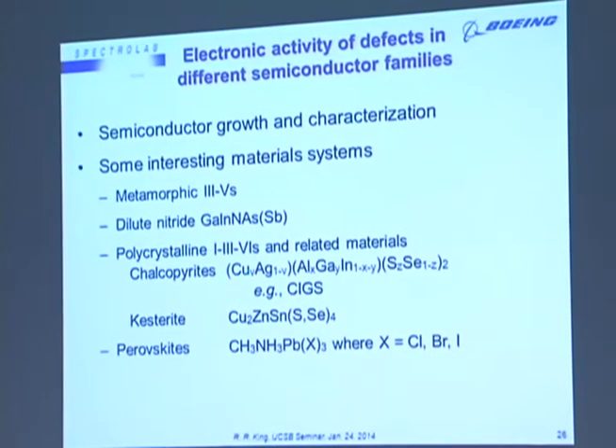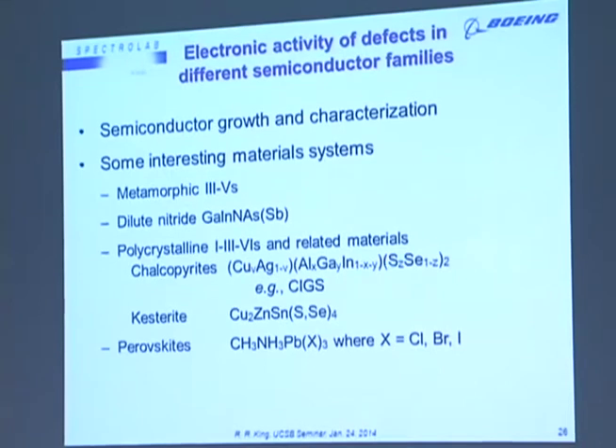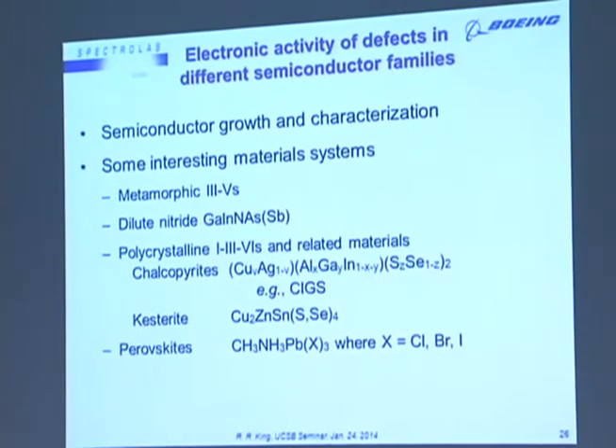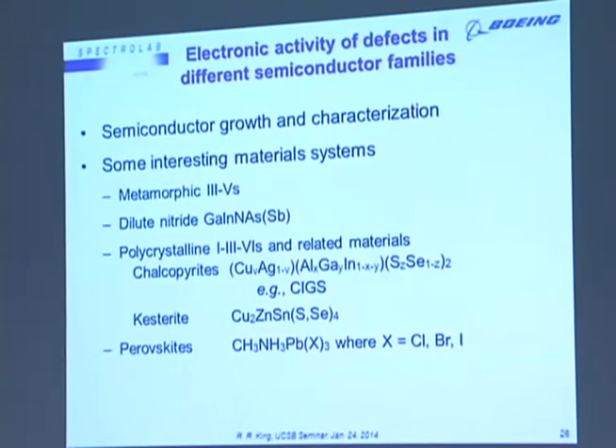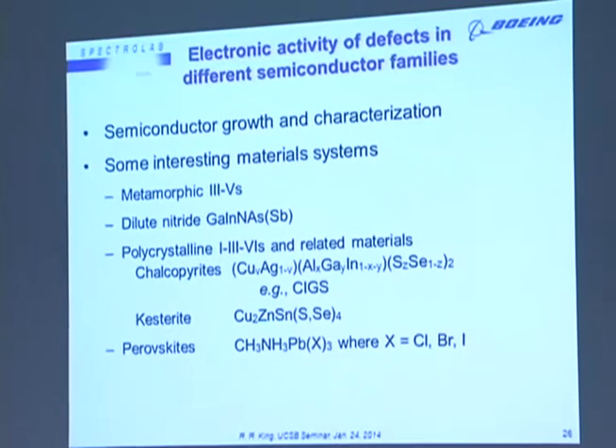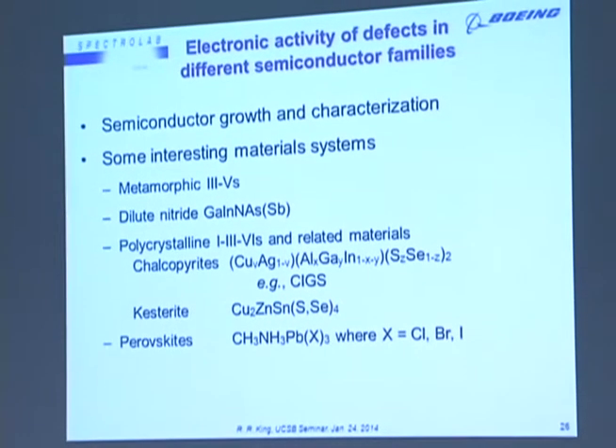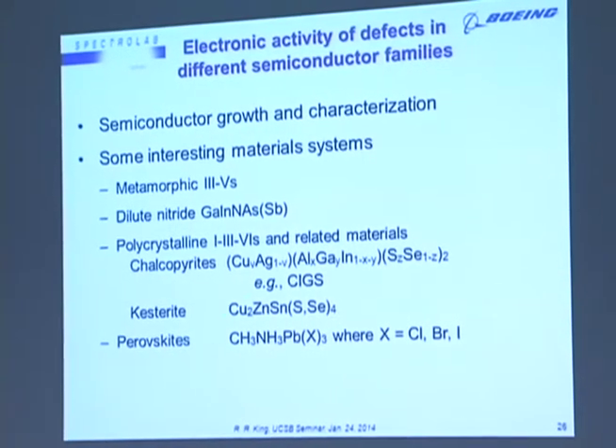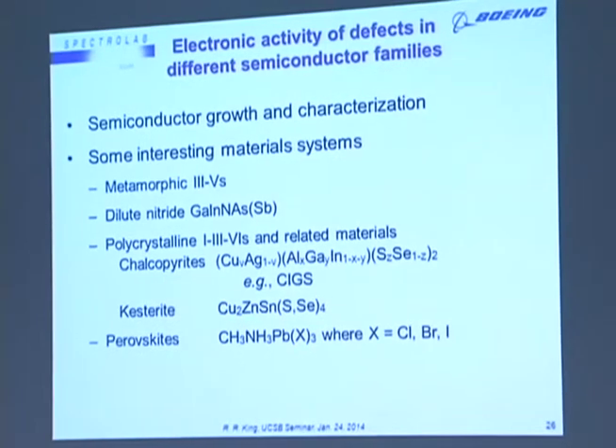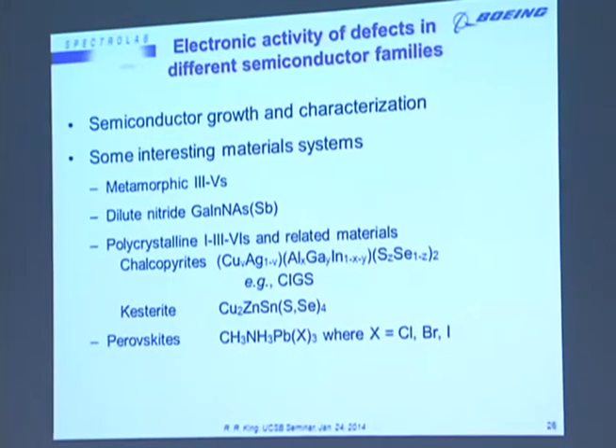So there's this chalcopyrite family, which can include a wide range of alloy compositions, including silver and aluminum, sulfur and selenium. We often just refer to that whole family as CIGS. And kesterites, which replace the group 3 by a combination of group 2 and group 4. And a new class of solar cell materials, which has been very exciting lately, perovskites, which have had a remarkable rate of progress in the short time that they've been researched. They're now up to 12% efficiency in a relatively short period of time in their development. But they are organic semiconductors involving a methylamine and a lead halogen composition.